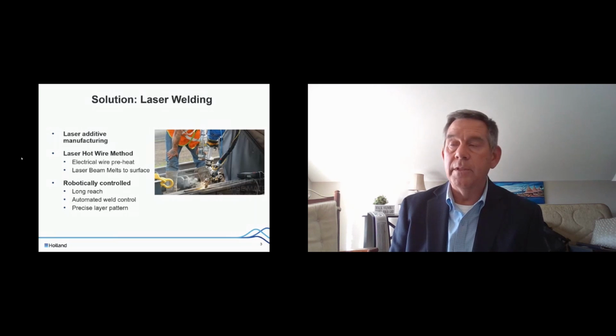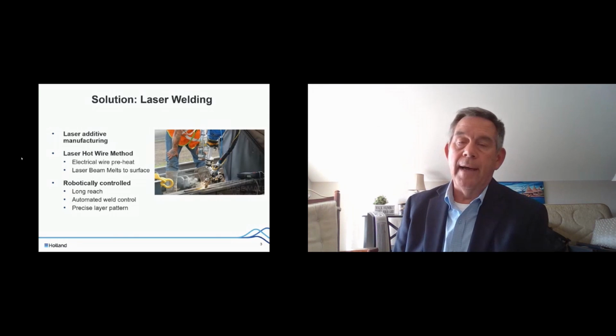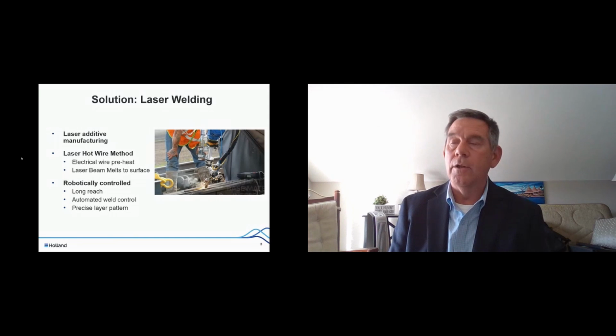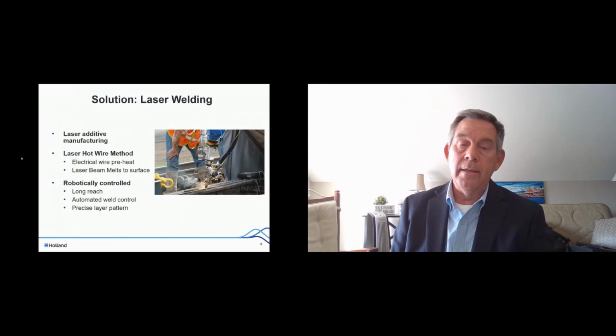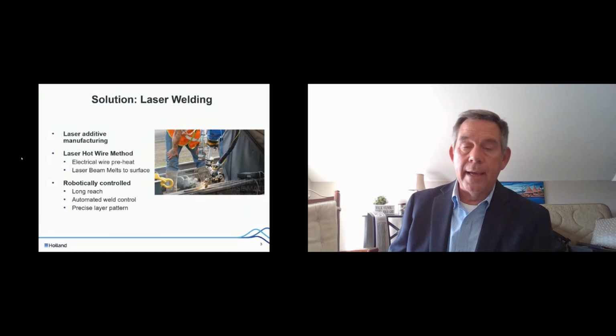Again, this is a manganese material that we're placing on a manganese frog. This provides a very precise process with significantly lower heat in the process as well. This is all done robotically controlled, so that provides a very long reach for the repair. It's automated so that each layer is laid down through the robot without an operator working the operation, and that provides a much more precise layer pattern and interpass layer materials.